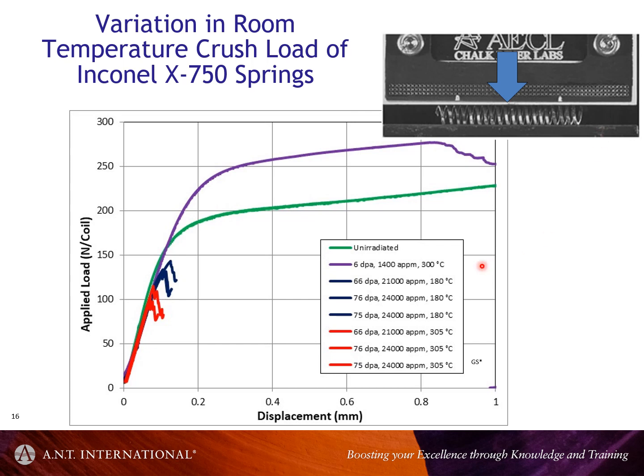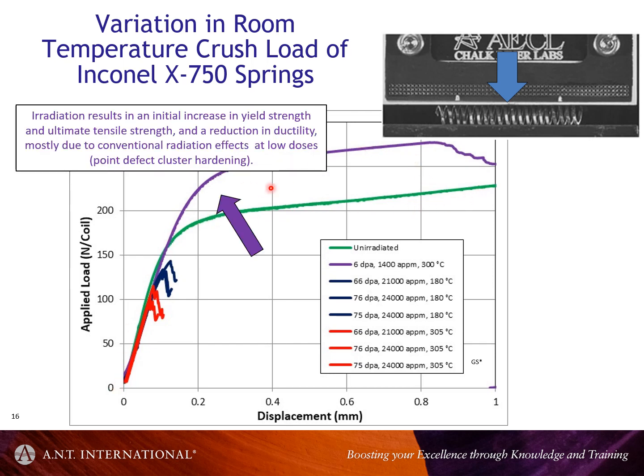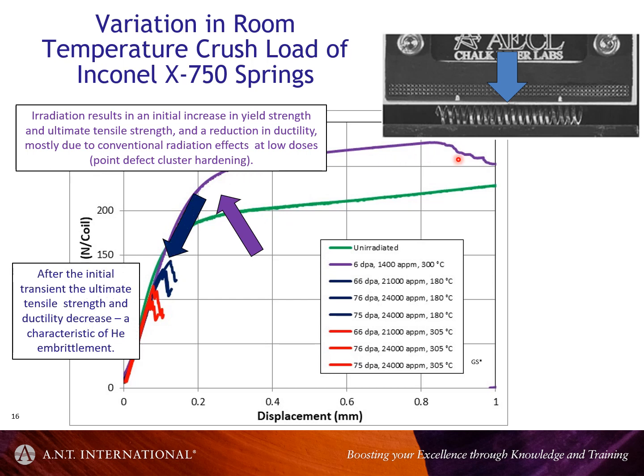But what we're seeing, if you look at the unirradiated material, is this load displacement curve. When it's irradiated to about 5-6 dpa, the strength goes up, and the ductility drops a little bit, as you would expect. But with increasing dose, the strength goes down a lot. So this is an issue, and a big concern for the CANDU industry, because will it keep going down?